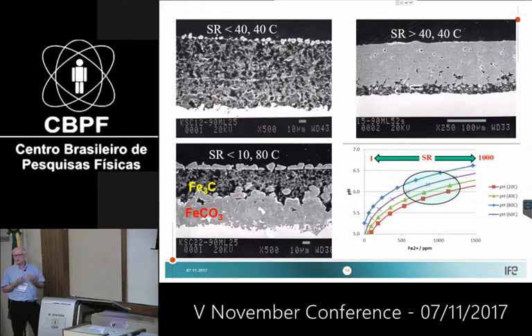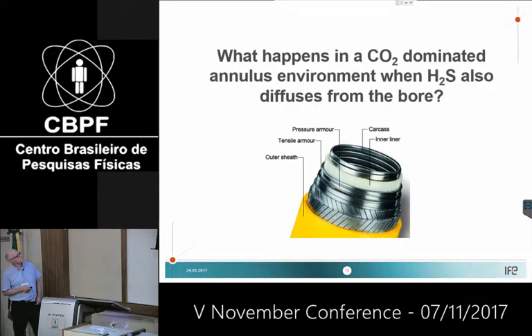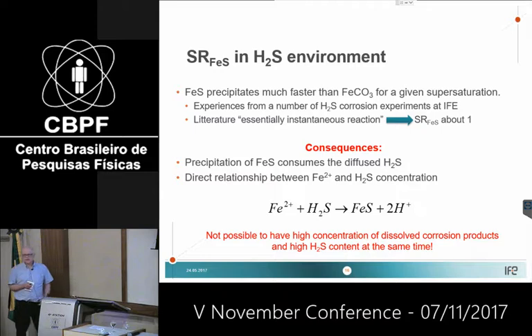So it becomes so important, what is my corrosion product level? And it's too complicated now to go into detail, but there are a lot of issues related to this level and how to predict or maintain such a level in an annulus. But what happens then if we get H2S into a CO2-dominated annulus environment? Since iron sulfide is precipitating so easily, we have experienced that you are always close to this saturation when you get H2S into the system.